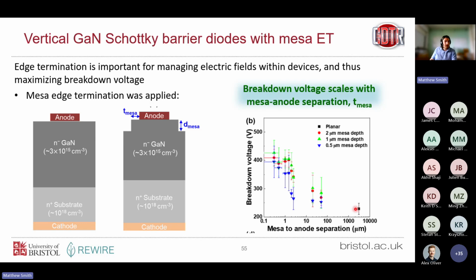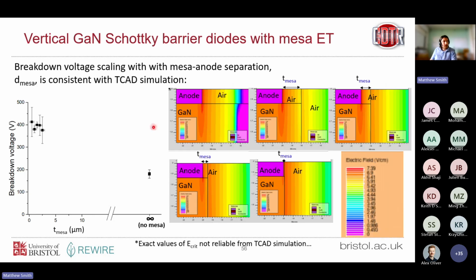So as we decrease our MESA anode separation, we can see a sudden increase in our breakdown voltage. So that's this parameter here. As we're making the anode and the MESA edge closer together, we increase the effectiveness of our MESA edge termination. So what's actually going on?